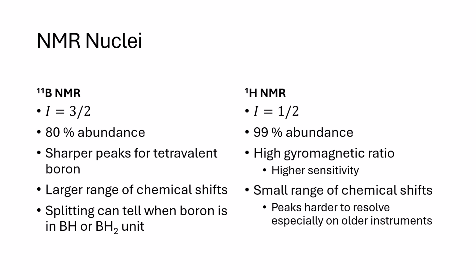There are two common nuclei used for the NMR analysis of boranes. The first one is boron-11, which is a quadrupolar nucleus of 80% abundance. Despite being quadrupolar, it does show sharp peaks for tetravalent boron centers.